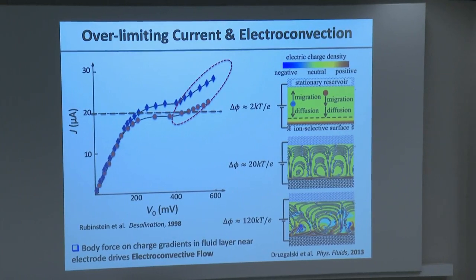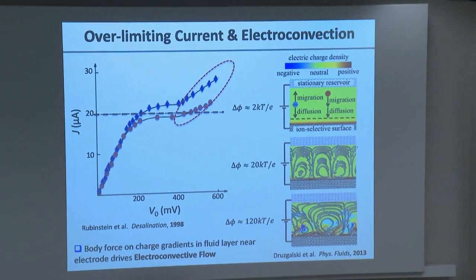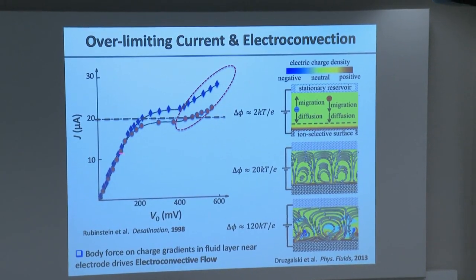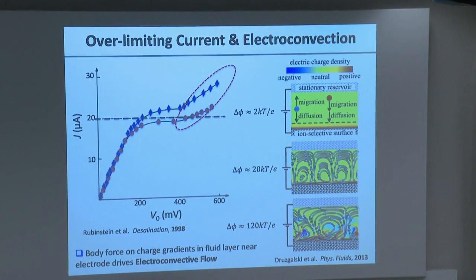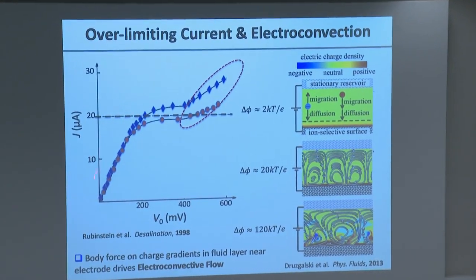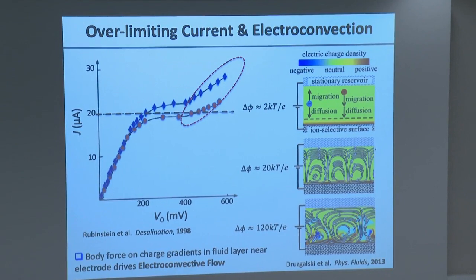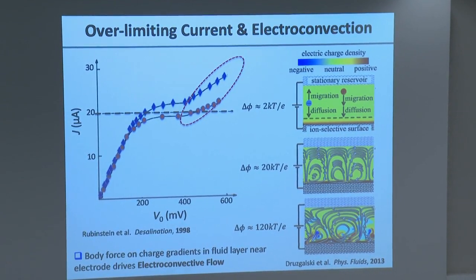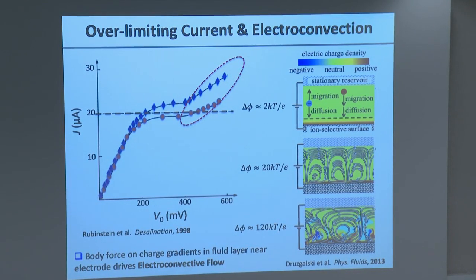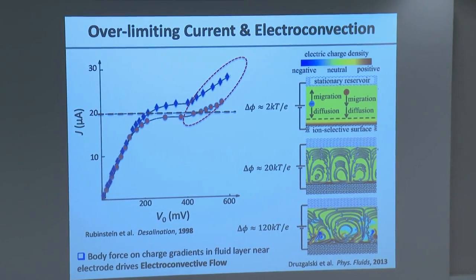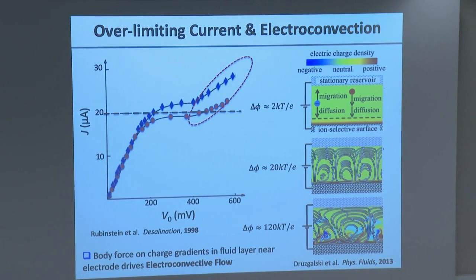Reality is very different. In fact, what people typically find is that if you measure the current versus voltage in an actual electrochemical cell, you in fact get the Ohm's law regime as predicted at low potentials, the linear regime. You in fact get this transition to the limiting current regime. But if you keep driving the system, what they observe is that you get an additional regime where the current starts to increase with voltage, and this is referred to as over-limiting conductance.